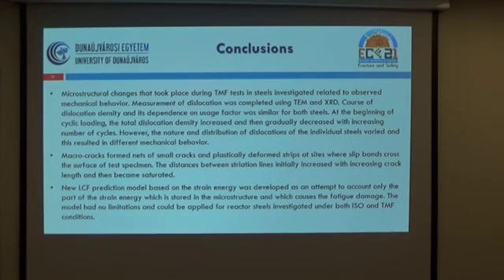There was another part of the work which was not included in the presentation because of the time limitation. I refer here only to the part that means we were able to separate that energy which generated the heat in the specimens during the fatigue process. This energy-based model had no limitations and could be applied for the reactor steels investigated under both the isothermal and the thermomechanical conditions.